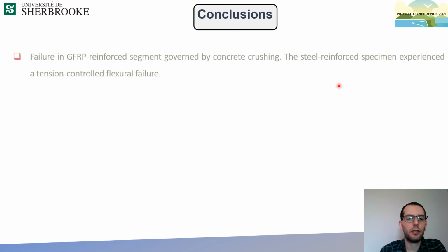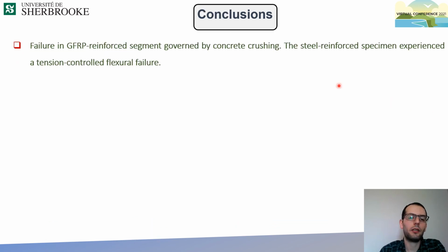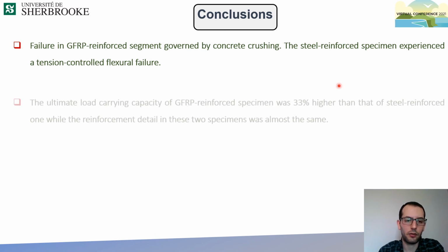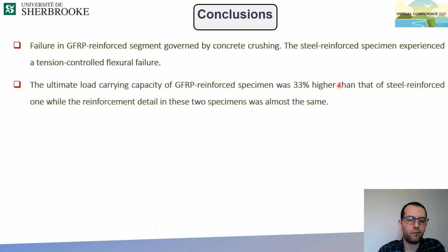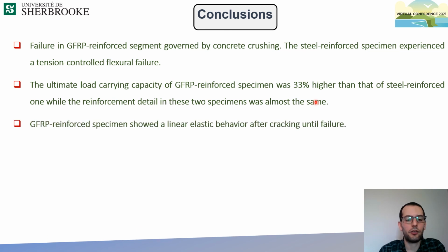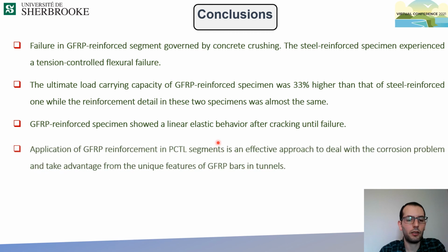We can conclude that the failure in the GFRP reinforced specimen was governed by concrete crushing, and the tension control flexure failure was observed in the steel reinforced specimens. The ultimate load carrying capacity of the GFRP reinforced specimen was 33% higher than the steel reinforced one, with the same reinforcement detail. And the GFRP reinforced specimen showed a linear elastic behavior until failure.